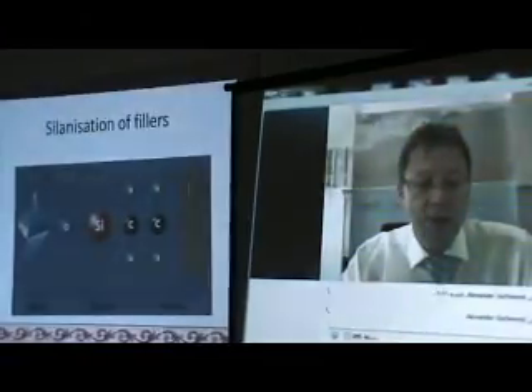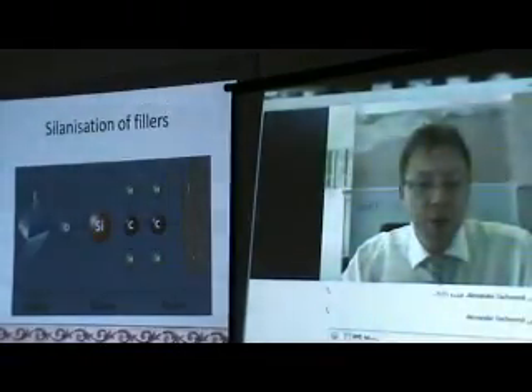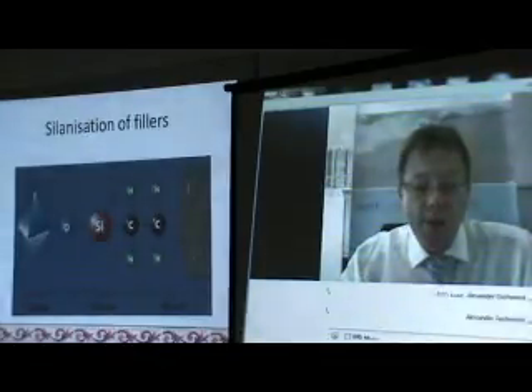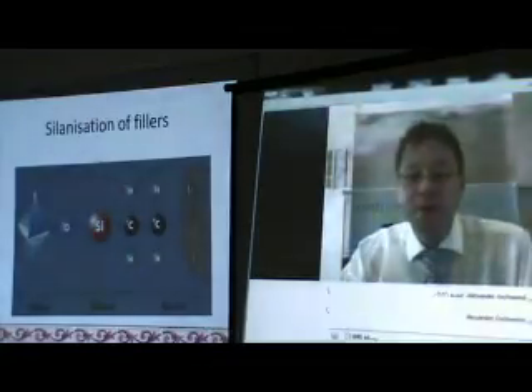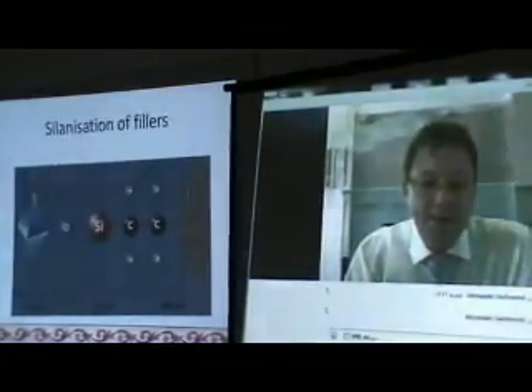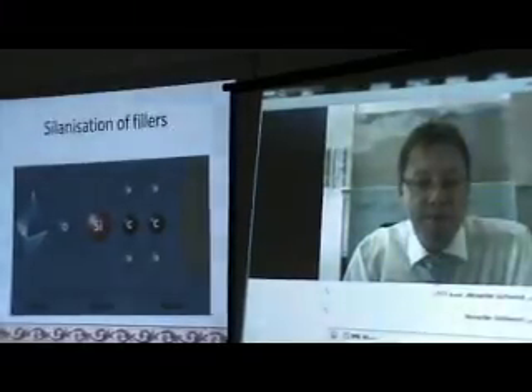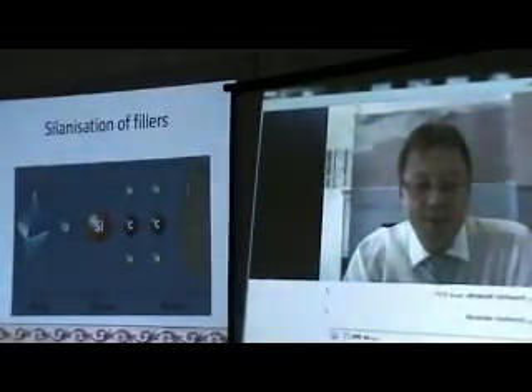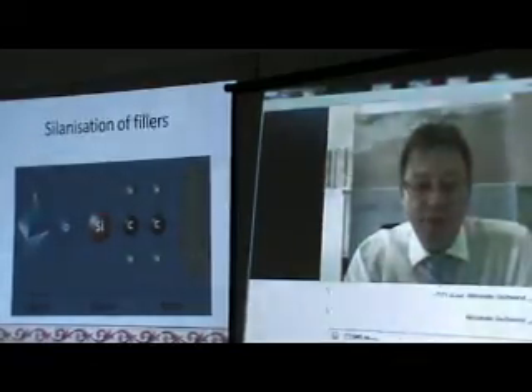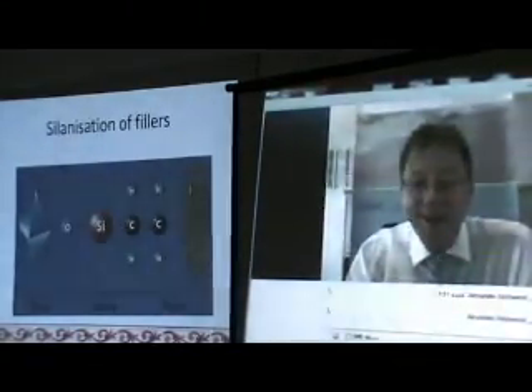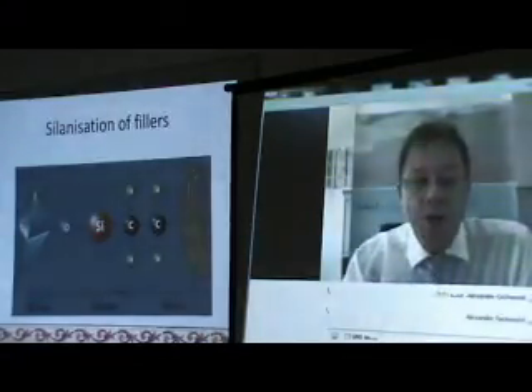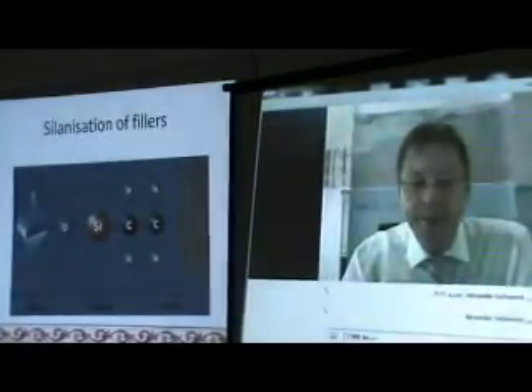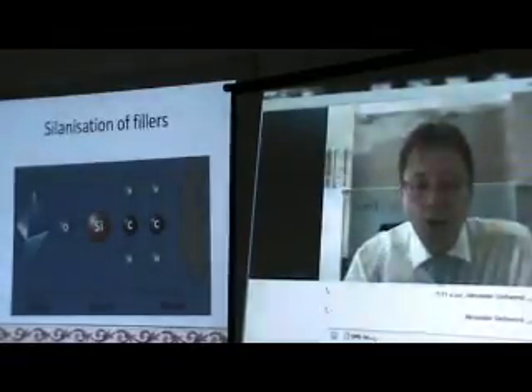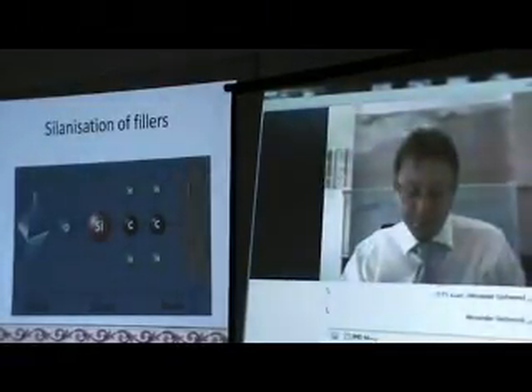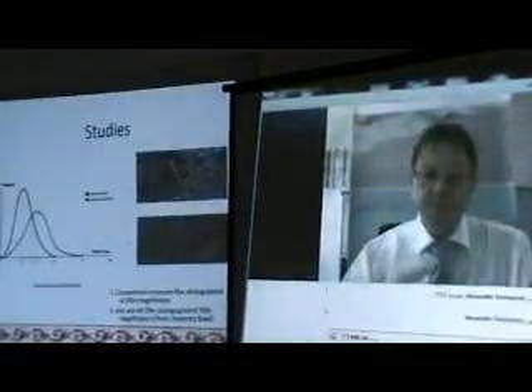Saremco has a very highly developed technique to have extremely good silanization of all particles. And as we have extremely fine particles, that means the silanization process is very important to have all the small particles well silanized, so that all of it is silanized but without any excess. Because if you have too much silane, then there will be the negative impact that there will be more shrinkage also. So all of these features are very important. Slide number 19, please.